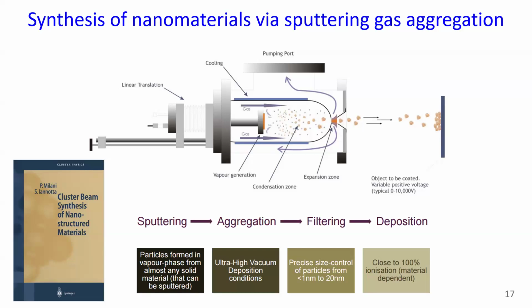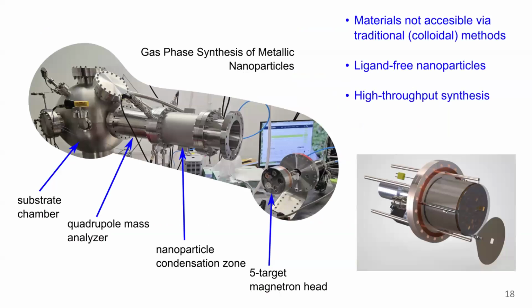And since this condensation happens in the vapor phase, it's a physically different process compared to chemical synthesis. In colloidal synthesis, your rate of forming nanoparticles is governed by decomposition of your precursors, whereas here it's a physical process that leads to nucleation and particle growth. And so that's the schematic. This is what our instrument looks like in the lab. We got this installed and running back in late October, so still very much in the preliminary phases.